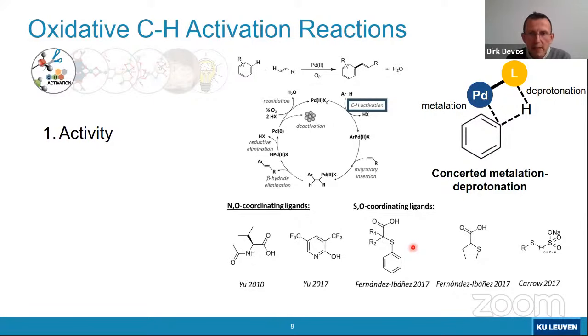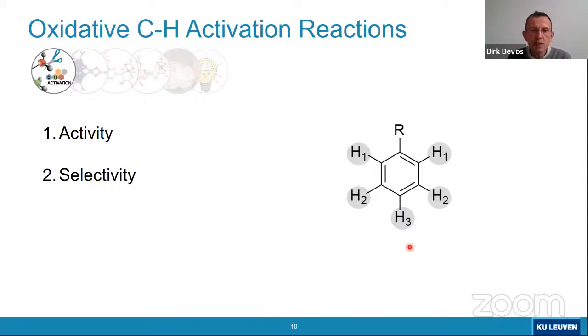Okay, so activity is a challenge and has been addressed in many ways. Another challenge which is really tricky and very difficult is selectivity. Indeed, if you have, for instance, a monosubstituted arene as shown here, then the question is always which of the CH bonds is going to be attacked? Is it going to be the ortho CH bond, which is relatively easy to activate, as we will see later on, or maybe the meta, or maybe even the para? And in many cases, it would be highly desirable to selectively activate the para CH bond, but at least in homogeneous catalysis, that goal is rather elusive or requires very complex approaches. So there has been, for instance, Ritter's recent approach with the thianthrenation intermediates that he makes, but in fact, it's a very involved approach if you think about it.